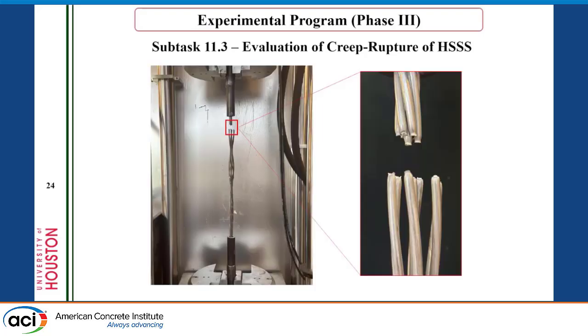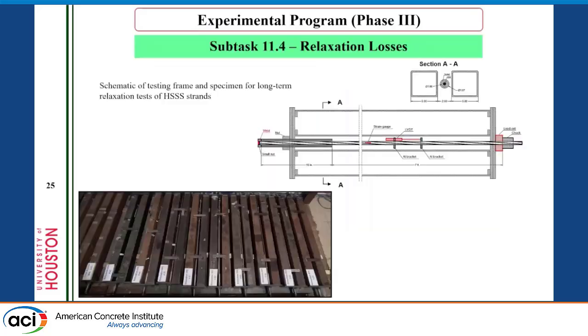This is one of the samples that we forced to rupture. We pre-stressed it at 92% for 4,000 hours, which is 4 times the test time limit. We added 2 kips and nothing happened, and we just forced it to rupture.